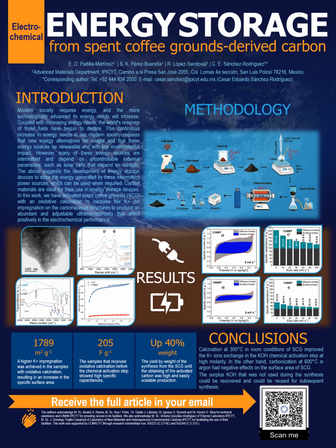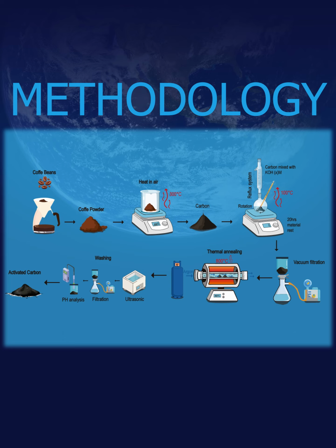So moving on to methodology, here is the complete scheme. We start by taking the coffee residues and we grind them into a powder. Then we gave it an oxidative calcination at 300 Celsius degrees for an hour, obtaining coal. The next step is to activate this charcoal using potassium hydroxide with a reflux system, giving it agitation and 100 Celsius degrees for 20 hours and 4 hours of static rest.